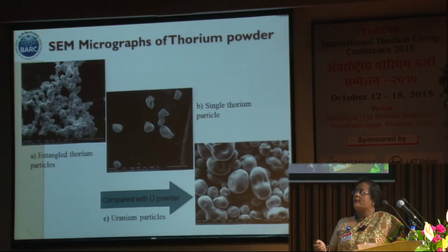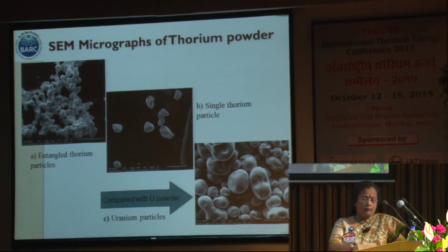This gives you the SEM micrograph of this thorium powder. These are single particles, and these are agglomerated. Here we give a comparison with uranium powder, which we also produce. You can see it is more spherical because of the lower melting point. After the reduction, when the primary particles are formed, they are more uniform, which is not so for thorium. However, after leaching, you can get a free-flowing powder from this also.